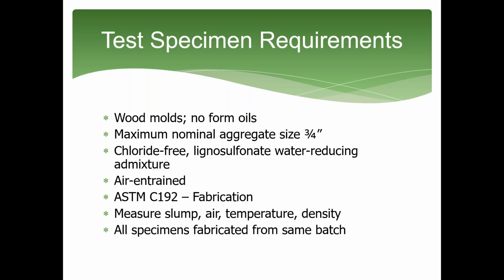Thank you, Kelly. The test specimen requirements are discussed in this section. We're using wood molds to fabricate the specimens. No form oils are used. The maximum nominal aggregate size that we're using is 3/4 of an inch. We're using a chloride-free lignosulfonate water-reducing admixture. The concrete mix is air entrained, and the fabrication is performed in accordance with ASTM C192. During the batching, we're measuring slump, air, temperature, and density, and all specimens from a submission are fabricated from the same batch of concrete.